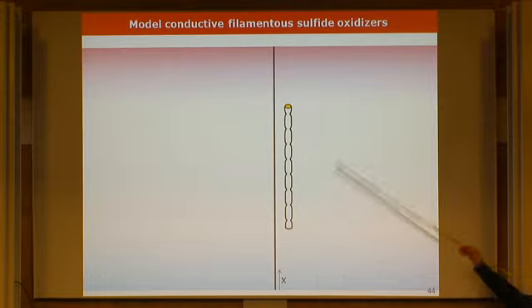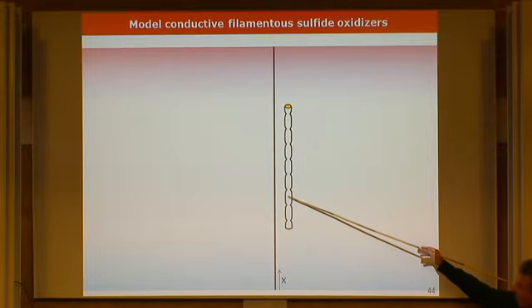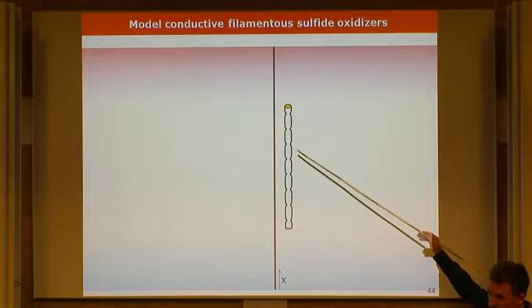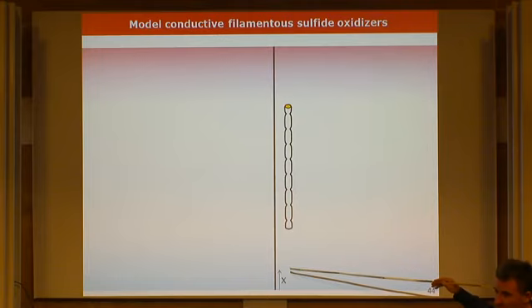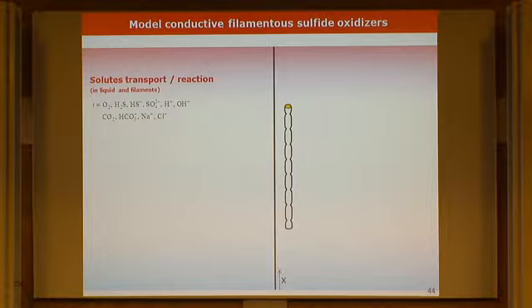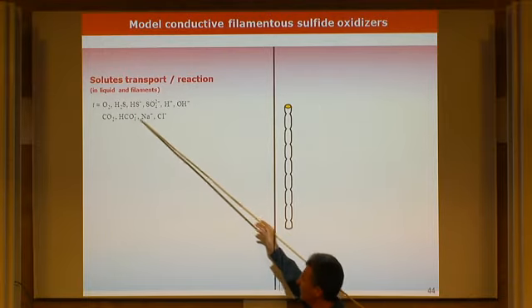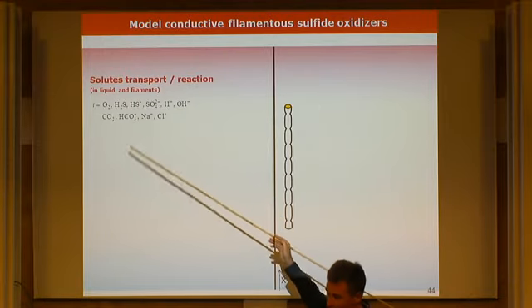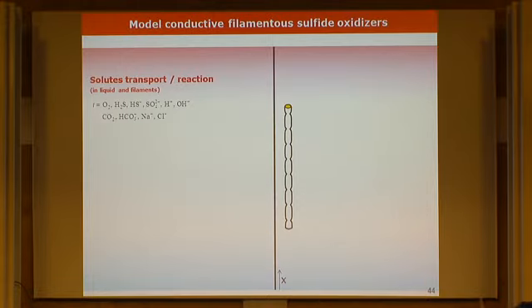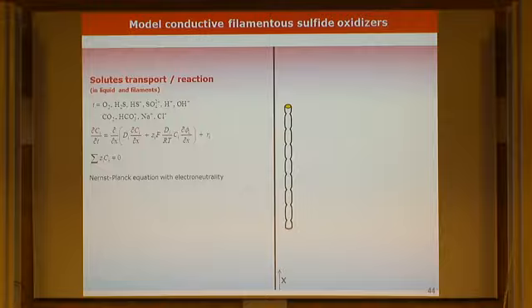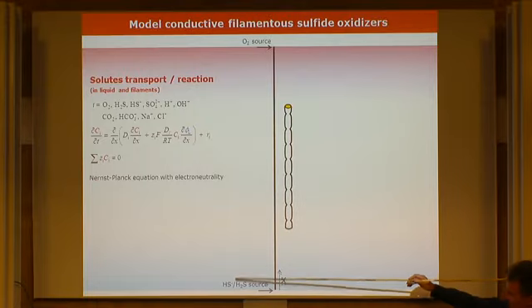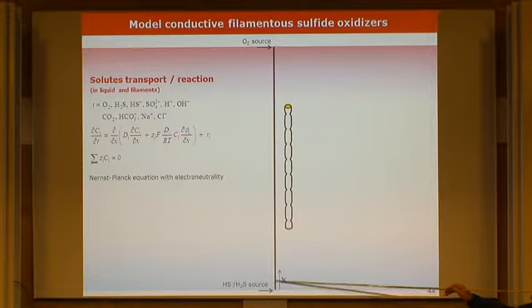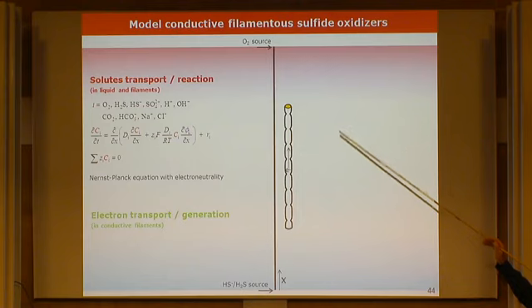Okay, so the domain is one-dimensional. This is the filament, but the domain is longer because you need a diffusive boundary layer for sulfide and one for oxygen at the top. So you have solute transport, a few essential chemical species with ions because you need pH calculation, so you need to speciate a bit. Of course, in the liquid phase you have Nernst-Planck, so diffusion and migration plus electroneutrality. You put a sulfide source at the bottom and an oxygen source at the top.